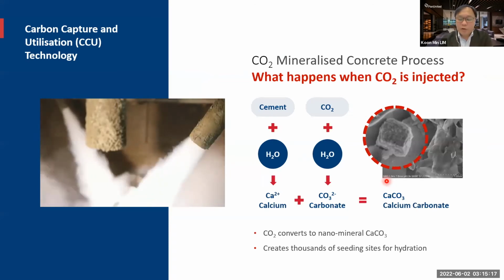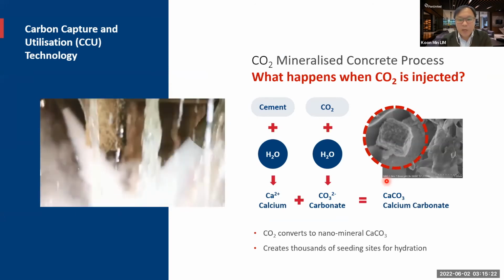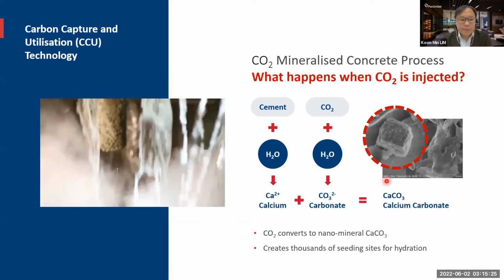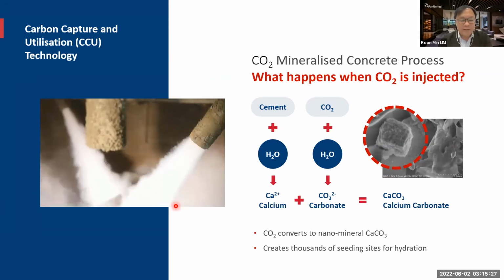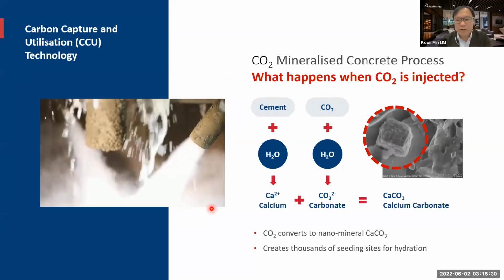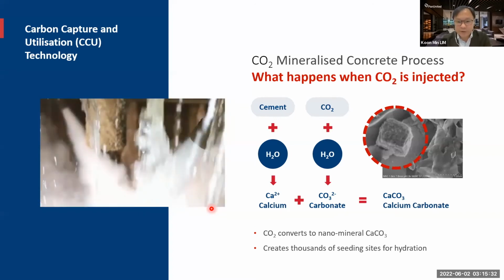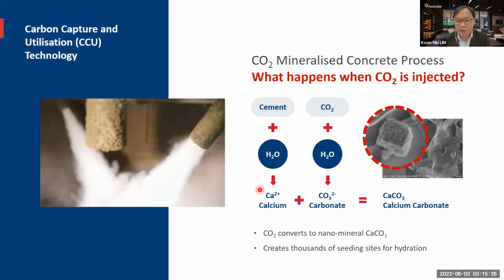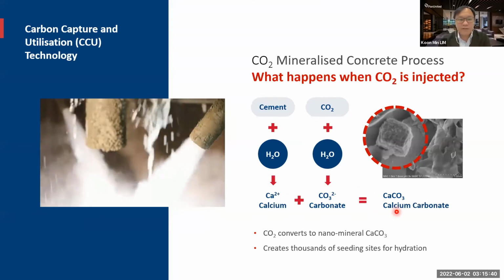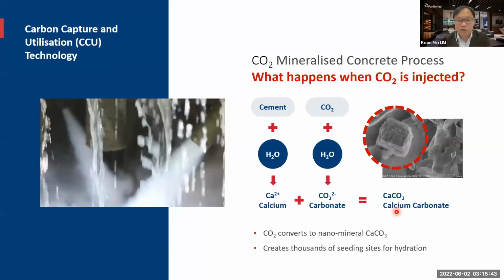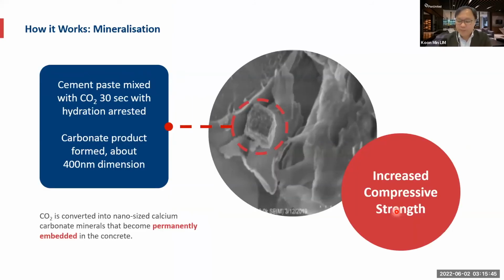So here's a snapshot of the chemical equation that goes through when CO2 is injected during the concrete production. This looping video shows that the CO2 is being injected during the concrete production in our central mixer. Through this reaction, nano-sized calcium carbonate is formed, and it actually creates thousands of seeding sites for hydration. So what you see here is a photo taken from a scanning electron microscope at 30 seconds after CO2 is injected.